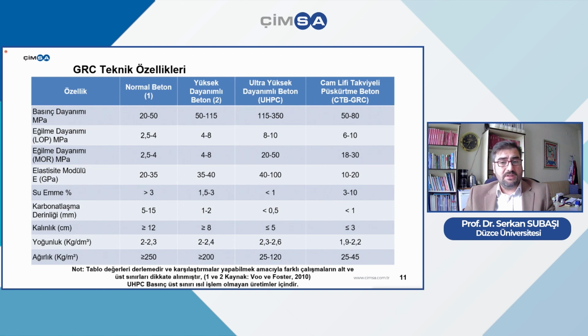In elasticity modulus, it's approximately 10 to 20 in gigapascal value. And water absorption is 3 to 10. In GRCs, of course, it is possible to make the absorption level higher. And because of its structure, it has a carbonation depth in millimeter values, and the thickness is changing between 10 or 15 millimeters in facade coating. And there are some, of course, thicknesses below 3 centimeters. And the density is changing between 1.9 and 2.2, and the weight is changing between 25 and 45 per square meter.